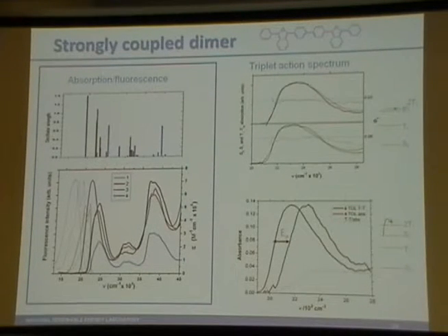And essentially what seems to be happening here is that we've pushed the lowest excited state, S1, down because we made this box so much bigger. But we've left the triplet essentially in the same place. And so 2 times the triplet now, instead of being about the same as S1, is now considerably above S1. And so for singlet fission to occur, you need more energy than just S0 to S1. You need this much more energy. And that's not an optimal situation.